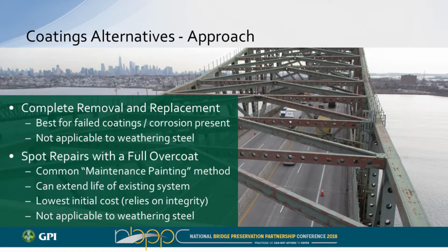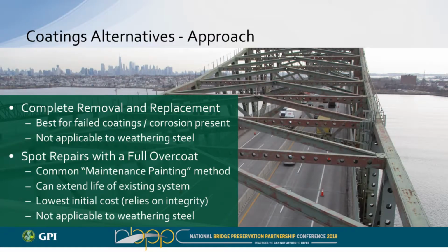We then have spot repairs with a full overcoat. In this case, if the majority of the coating system is in good shape and has good adhesion, you can just focus your efforts on the areas that are failing or that have some corrosion: spot clean, prime, and paint those, and then overcoat the whole structure, the whole member, so that it looks nice and uniform. Very common maintenance painting method. It can extend the life of the existing system, and that's what they had done more than 20 years ago, this overcoating type method. However, it does rely on the integrity.